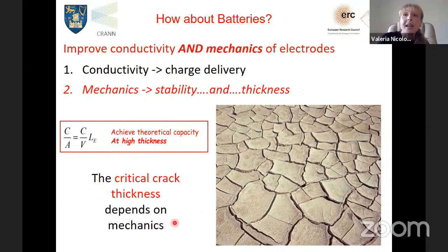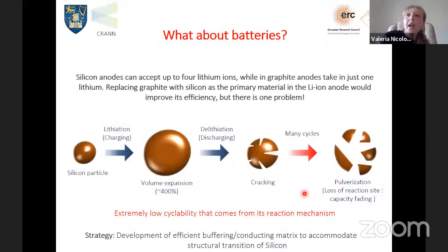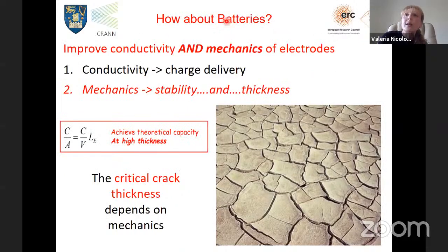But the problem is that with the conventional materials that are used for electrodes in the market, you cannot go beyond a certain thickness, because you start getting what we call critical cracking behavior, where the thickness is getting so high that the electrode starts falling apart. So we thought how to solve this issue, and we thought that we could have some solutions towards these 3 points.